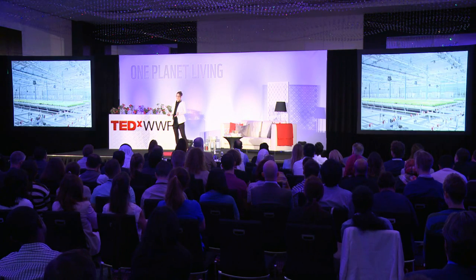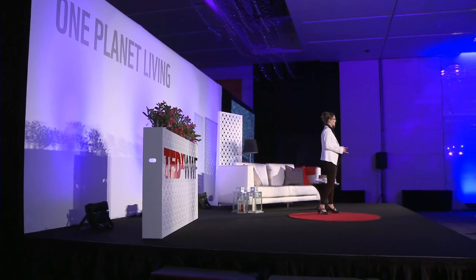Currently, I'm working with teams in both the U.S. and the UAE to scale up this process for producing high-volume batches of these bricks at a time. What we have found is that the process for growing bricks is similar to how we manufacture plants in greenhouses. Instead of using fire to harden the bricks, a process for growing them with irrigation to feed the bacteria is used. Since these bricks are alive, they require multiple feedings of solution, and are made in ambient temperatures. Once the bricks have reached the desired hardness, they are simply dried and ready for use. As for the bacteria, once their food and water supply has been cut off, they simply die. The irrigation solution is fully recycled in a closed-loop system — important to save water resources, and to capture a natural byproduct of the bacteria, which is recovered as a natural fertilizer.